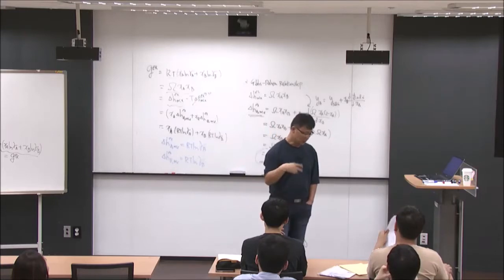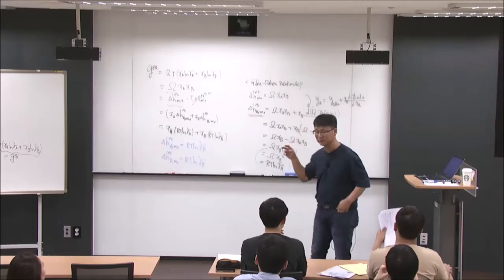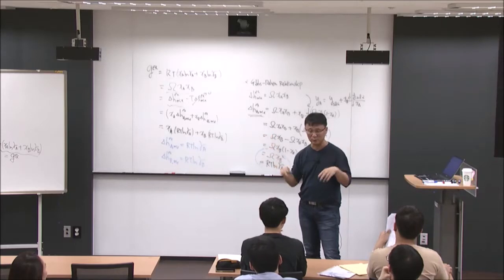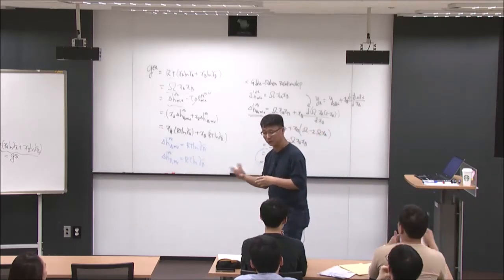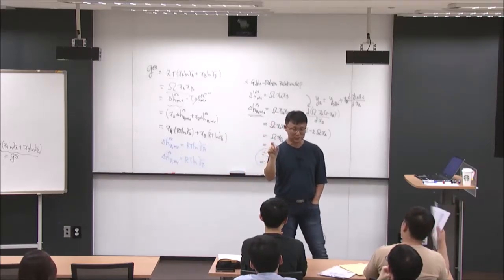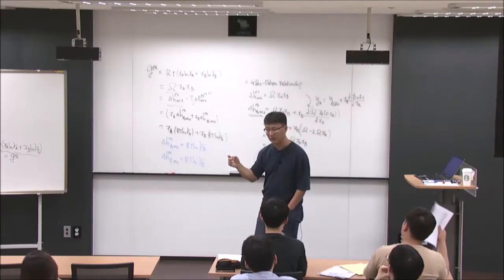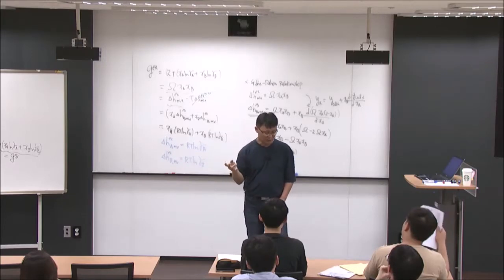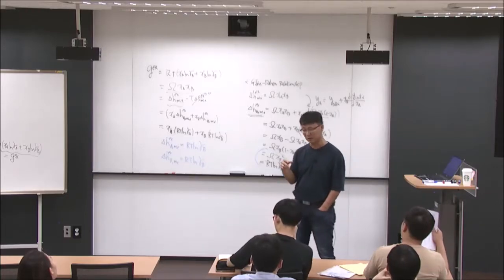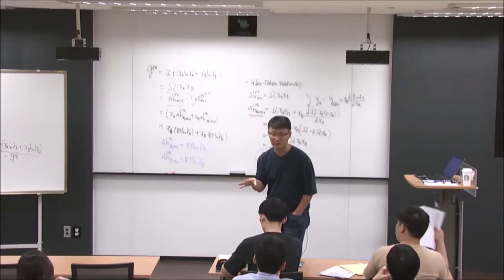Okay? And then activity is given by the activity coefficient times the mole fraction. This is a very artificial definition, because we want to define the activity as a function of composition, so we add the composition component inside the activity. So activity is the activity coefficient times the mole fraction, and the activity coefficient changes depending on the temperature and the composition, because it represents the interaction of your species with the other surrounding species in the solution.